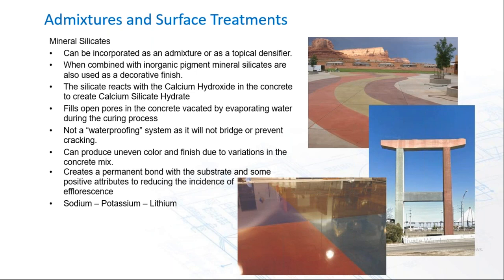The silicate reacts with the calcium hydroxide in the concrete to create calcium silicate hydrate. This, much the same as the crystalline treatment we saw on the last slide, fills the open pores within the concrete vacated by the evaporating water. Again, not really a waterproofing system, as it will not bridge cracks or prevent cracking. When used as a coating, it can often produce an uneven color and finish due to the variations within the concrete mix. It does create a permanent bond with the substrate and has some positive attributes in reducing the incidence of efflorescence.